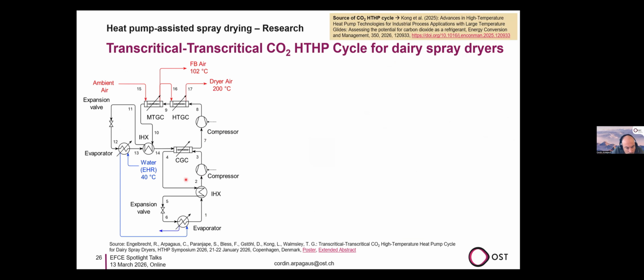I know it's maybe too much into detail, but what is the message here? What is the application? We have ambient air comes in with, I don't know, 15 degrees, and then a first gas cooler from the heat pump. And then we have 102 degree air for the fluidized bed, and another part of the air comes out at 200 degrees. That's the heat sink side. And on the heat source side, we would use the water from the exhaust stream of the spray dryer.